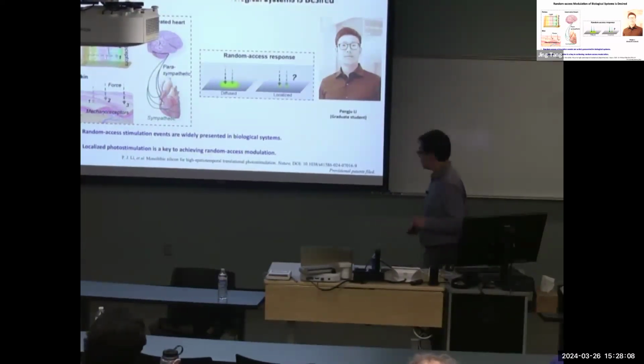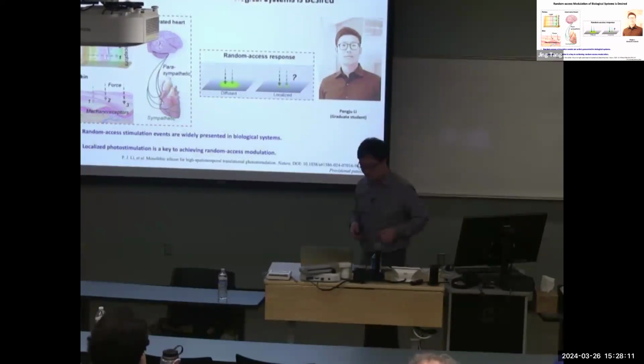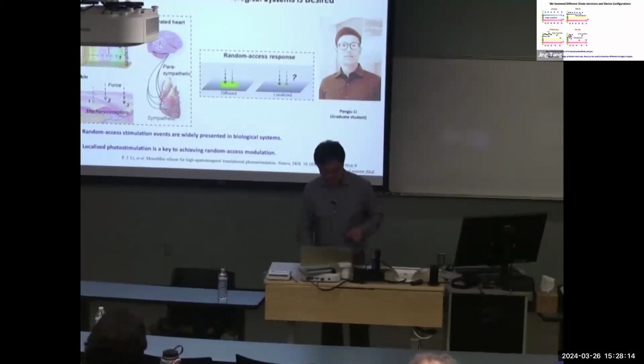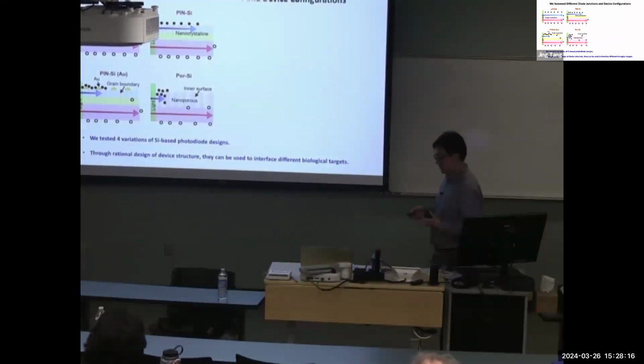So how can we tackle that? This is probably one of my best graduate students, Punjuli, and he recently really made this happen. I won't go into the specific details, but he has screened multiple silicon-based heterojunctions, including the commercially available single crystalline p-n junctions. The different colors represent different doping types, p-type and n-type. Then pin silicon, so p-type silicon, a nanocrystalline intrinsic layer, and a nanocrystalline n-type layer. So it's pin. And then pin, but decorated with gold nanoparticles on the top surface of the n-type nanocrystalline layer. And finally, this nanoporous silicon that I mentioned earlier today.